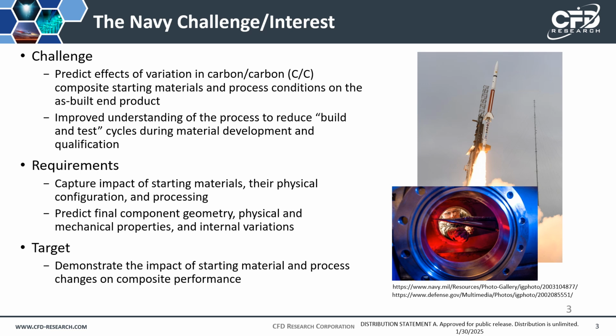For this effort, the Navy challenges and interests strongly overlap with the Air Force concerns outlined in the original topic. The carbon-carbon composite materials that both these agencies and others are interested in for structural applications in extreme conditions, particularly very high temperatures, are complex systems and can be difficult to produce repeatably. Fabrication is typically a multi-step process, beginning with woven carbon fibers arranged in the desired shape. Resin is infiltrated into the fibers, then heat-treated to form a carbon matrix that is bonded with the carbon fibers. As some material was lost during the heat treatment, this infiltration and pyrolysis heat treatment is continued over multiple cycles. The details of the as-produced composite structure and the resulting mechanical performance and properties depend on both the starting materials and the process conditions that are used during the fabrication.